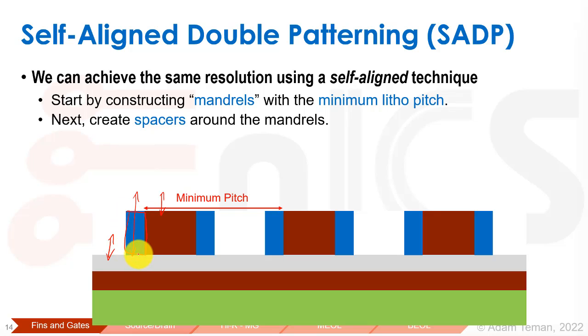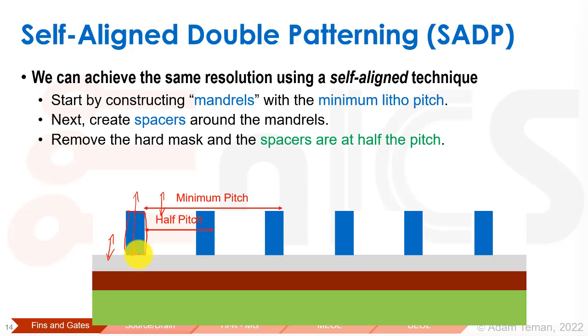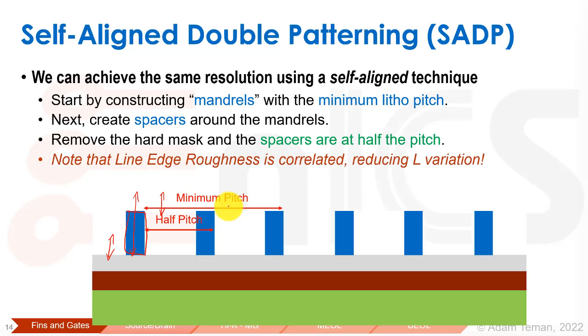And again, we use this for making things like lightly doped drains in planar technologies, but now we actually use it to make a spacer around the mandrels. And now we can just remove the mandrel itself, and we get some sort of a pattern that has half pitch from the minimum pitch, and it's completely self-aligned. It's really nice. So we remove the hard mask, and the spacers are at half of the minimum pitch, and that's really good. That way we got a higher pitch density than we could have with standard lithography. And you also have to note that the line edge roughness is correlated for both sides of the mandrel, so it really reduces the linewidth variation, and we got a win-win situation.